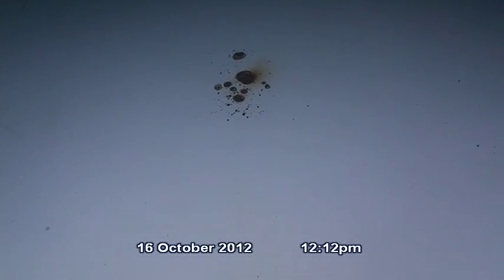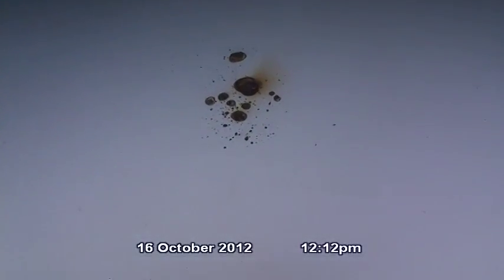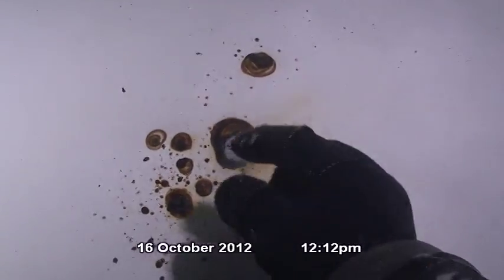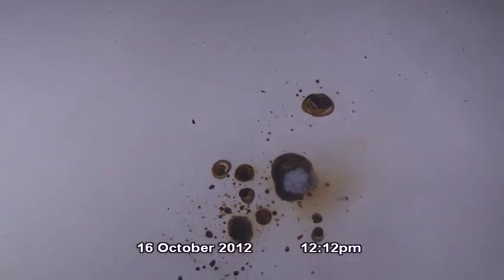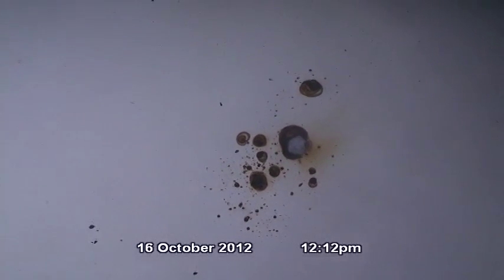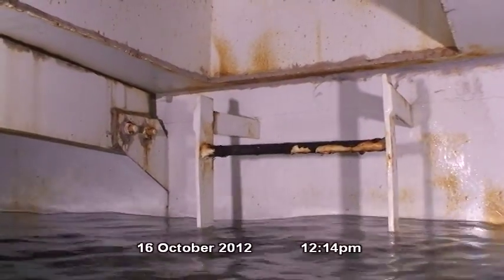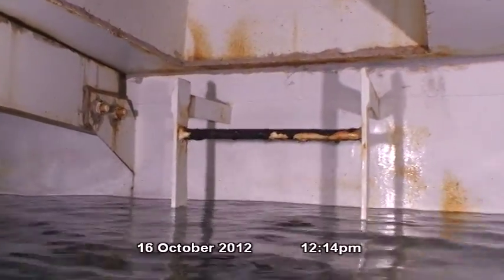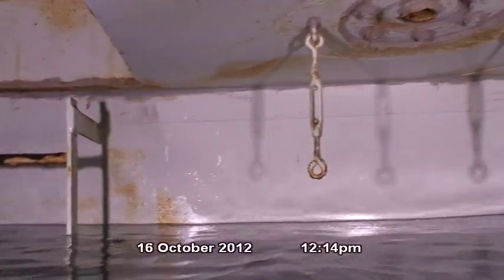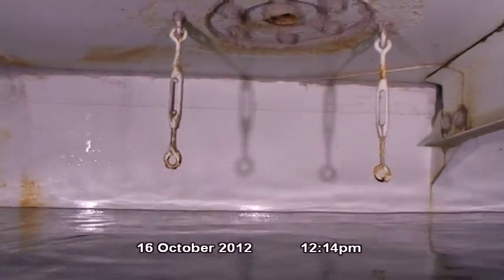Here's another example where metal loss is taking place on the floor. In this location, the corrosion nodule was removed. Slight metal loss is taking place in this area. It should be noted that in all of the areas on the floor where the diver removed corrosion nodules, slight to moderate metal loss is taking place. Metal loss is also taking place on the top 3 ladder rung rails.